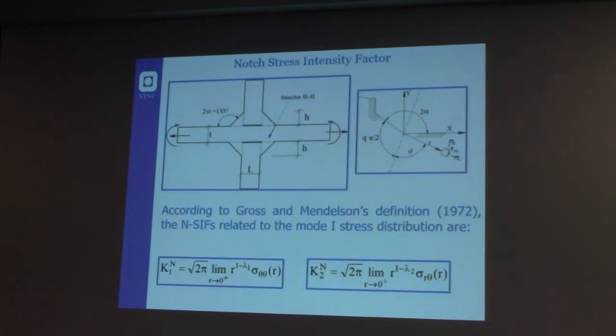I said before that weldments are always a kind of extension of sharp notch. If you consider a weldment, usually we have a notch opening angle of 135 degrees, and at the root we have a notch opening angle equal to 0, so we have a crack, or we have a notch opening angle that is 135. We can apply the notch stress intensity factor for design purposes, considering the stress singularity.